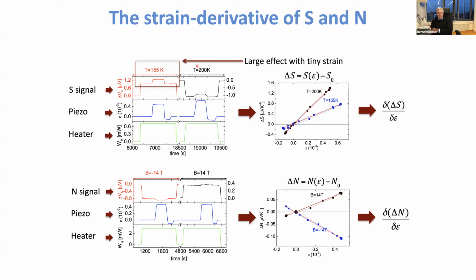And that's here measured at a different temperature. And you see the Seebeck effect is negative and the strain effect is still positive. So you can really discriminate these two things. What we then do is measure these small effects as a function of strain plotted in this way. From the slope, we then get the change of the Seebeck effect as a function of strain. And the same you can even do for the Nernst effect, which is a little bit more complicated because now you have to apply also magnetic fields, negative and positive ones, and you have to subtract the things. But also here, you can easily follow the change of the Nernst effect as a function of the strain.